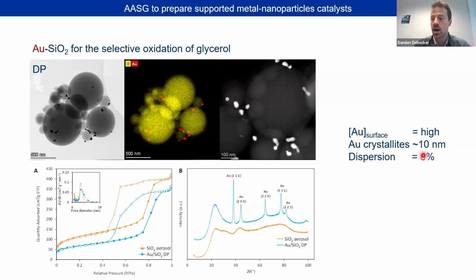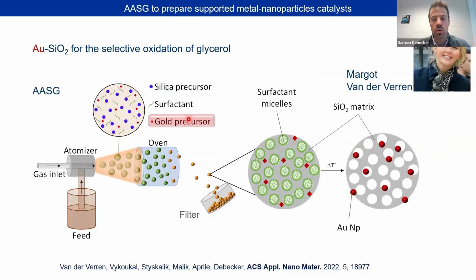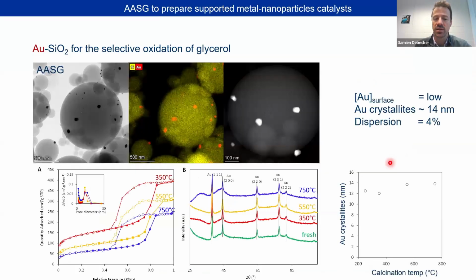So we thought, okay, let's try our magic with putting the gold directly in the synthesis and hope that we form small particles dispersed in our silica. When we tried that, this is what we ended up with. Again, those quite big black, red, or bright spots indicative of large gold particles. And indeed, large particles were detected if we check the XRD signal. When we analyze them by XPS, we have a very low surface concentration because most of those particles, or some of those, are actually inside of the spheres and not on the surface. And if we measure the dispersion, so the accessibility of this gold is very, very low.